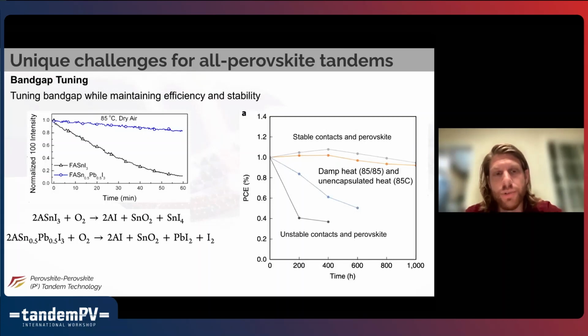So you really slow down that oxidation. And when you choose your composition correctly, and this is not a linear effect with tin content, this is an exponential effect, and if you choose your contacts right, your composition right, and your processing right, then these low band gap solar cells